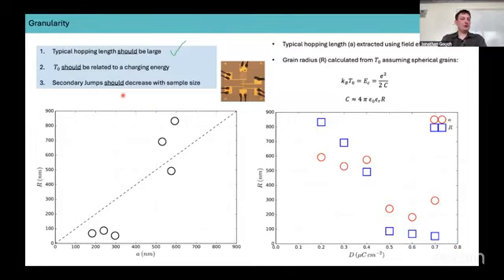This granularity model also relates to secondary jumps, which we observe in our sample. We've been fabricating these samples, which are quite interesting because they're essentially a single Hall bar that decreases in size as you move down the Hall bar. This top sample here, apologies, it's quite small, would be 200 by 200 microns and 100 nanometer thickness. Then as you move down the sample, you move to this sample, which is typically 5 microns by 5 microns. As it's all in the same Hall bar, you can damage the whole sample in one go using the ion beam. So you don't get this disorder variation between samples. This is currently a project that's still ongoing.